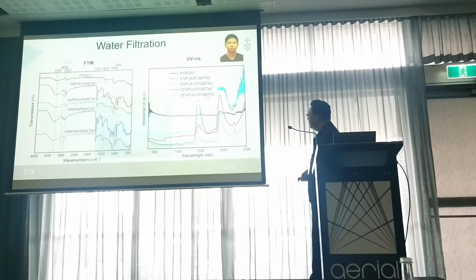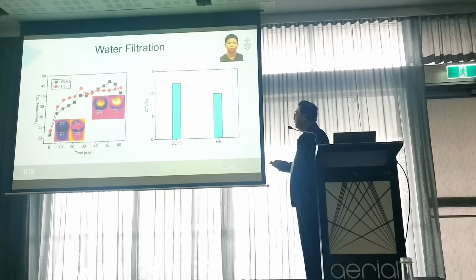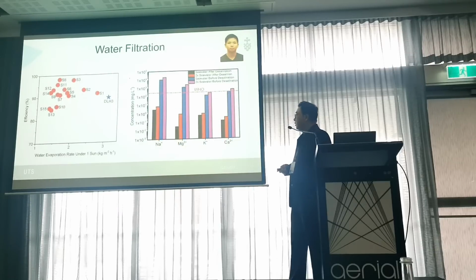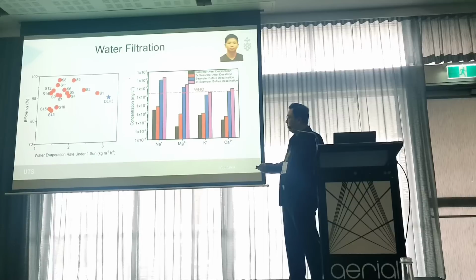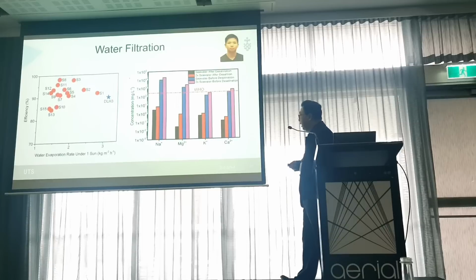So we characterized with FTIR and UV-vis, and first we demonstrated that the dual-layer configuration can enhance the heat insulation. We tested the temperature of the interface and the bulk water and observed a higher temperature difference compared to the conventional homogeneous system. We also tested the evaporation performance, at 3.1 kilograms per square meter per hour. But more importantly, these hydrogels show a high salt rejection ability. So we tested the ICP performance against seawater from Sydney Bay, and also concentrated seawater.